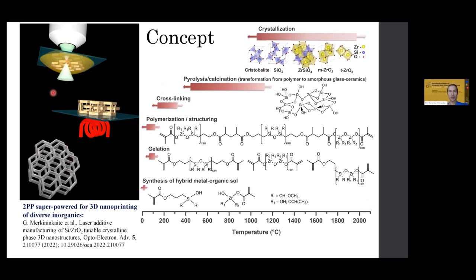We develop, we get the 3D structure, and then heat it at elevated temperatures, typically 1000 or even higher, whether in inert atmosphere or in ambient air, and remove the organic part. So all the acrylates, methacrylates, or epoxy or whatever materials it would be, the organic compounds containing carbon and hydrogen will evaporate and will result in an inorganic substance, but will be preserving the defined 3D shape. So we'll get the 3D structure printed via photopolymerization, but without the polymer itself, without the left organic particles. This technique was developed to a great extent by Greta Merkininkaitė, and we can call it two-photon photopolymerization or laser direct writing, superpowered by the option to print inorganic materials.